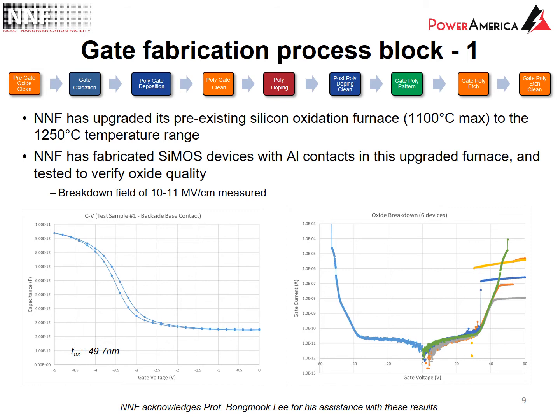of the device itself. The first thing we had to do with NNF was upgrade a pre-existing silicon oxidation furnace, because this pre-existing furnace only went up to 1100 degrees C. And as mentioned before, silicon carbide is a much higher temperature material, so we needed something that would go up to 1250 degrees C. So with Power America's support, we were able to make that equipment upgrade. And once we did that, the first thing we had to do was validate the performance of this upgraded furnace.